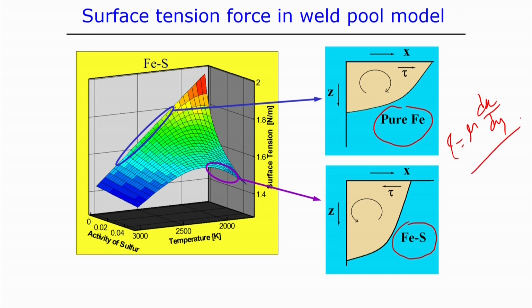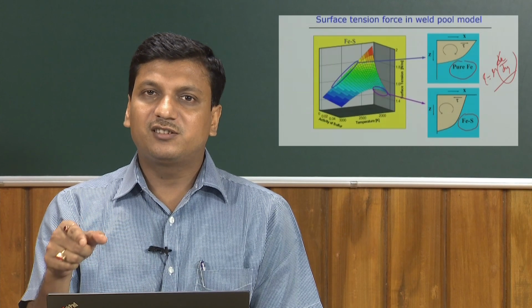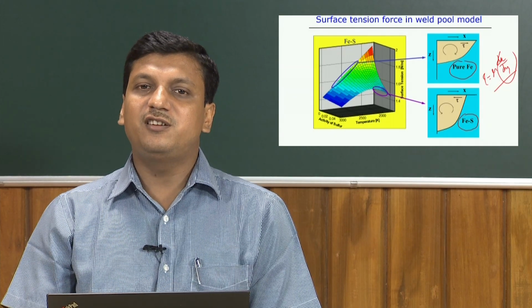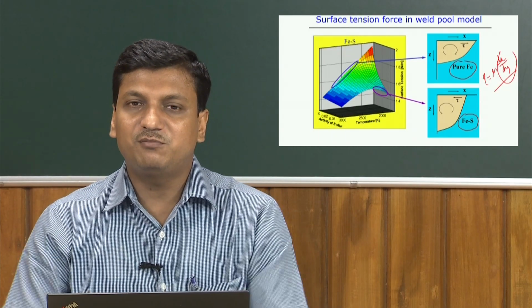So, that shear stress acting on the surface is not in the outward direction, it is acting in the inward direction, and that shear stress basically comes from the nature of the surface tension force, and that shear stress is linked with the velocity gradient. So, that means the metal is flowing from the outward periphery to the center direction, which creates a metal flow in an anticlockwise direction. It is completely reverse from the pure iron system, the pure Fe system.